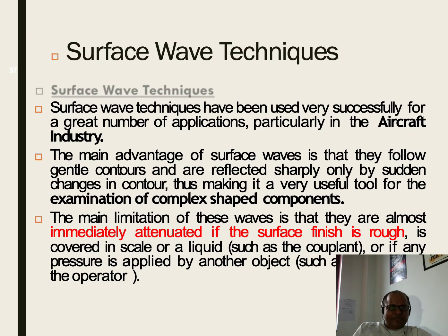Surface wave techniques have been used very successfully for a great number of applications, particularly in the aircraft industry. The main advantage of surface waves is that they follow gentle contours and are reflected sharply only by a sudden change in contour, making them a very useful tool for the examination of complex shaped components. The main limitation of these waves is that they are almost immediately attenuated if the surface finish is rough, is covered in scale or a liquid, or if any pressure is applied by another object.